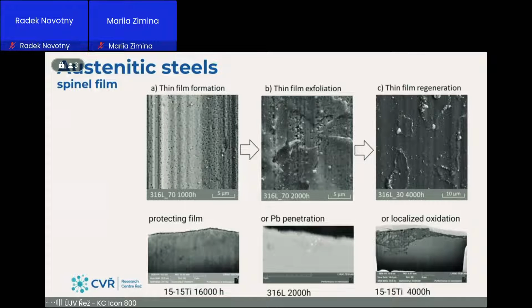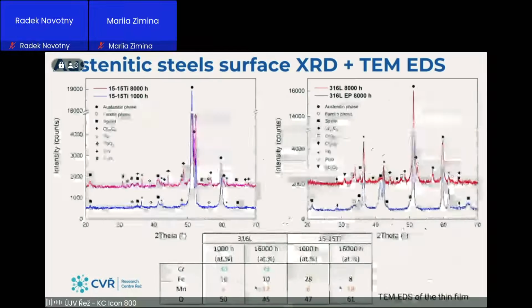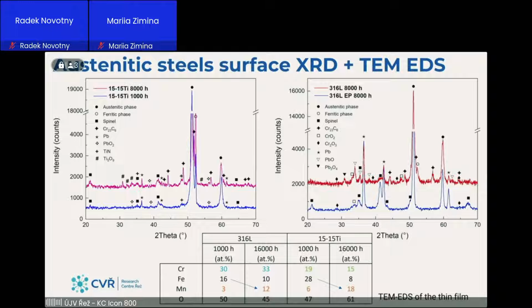That exfoliate and regenerate, and it can be present here even after 16,000 hours, or it may fail and then some lead penetration occurs or localized oxidation. We try to identify what's the composition of this very thin layer that is, let's say, 100 nanometers. It's really hard to do. So we combine the XRD with TEM to eliminate the amount of phases. And we figure out it's a very interesting spinel phase that has some kind of dynamics over the time of exposure.